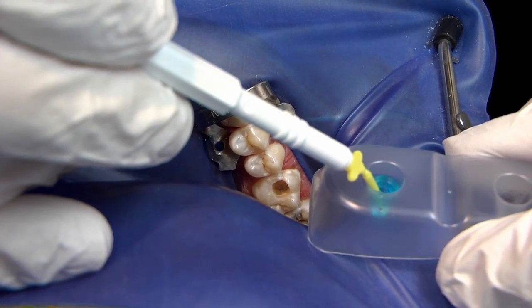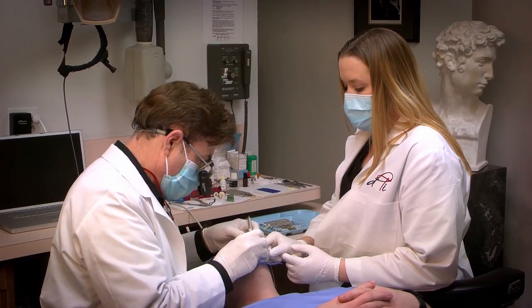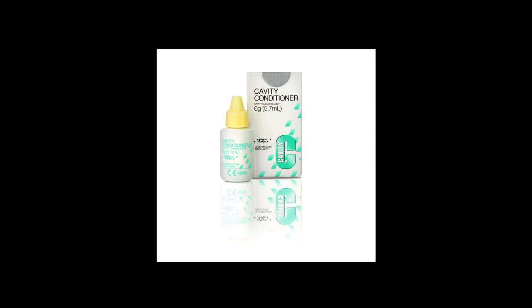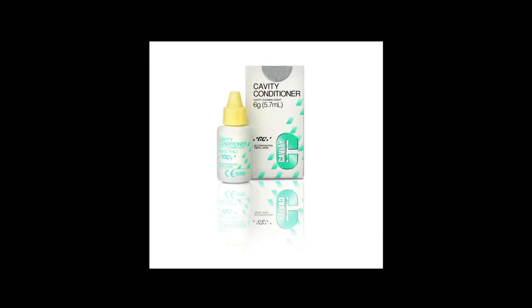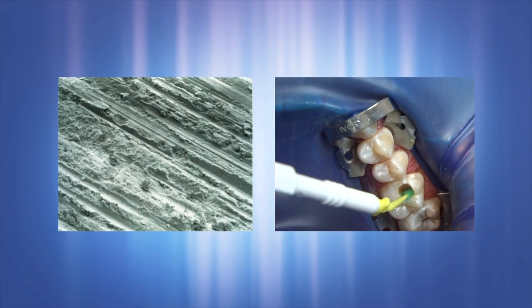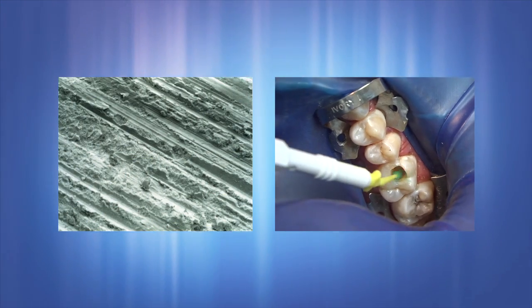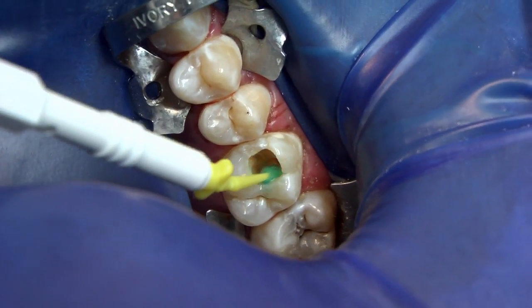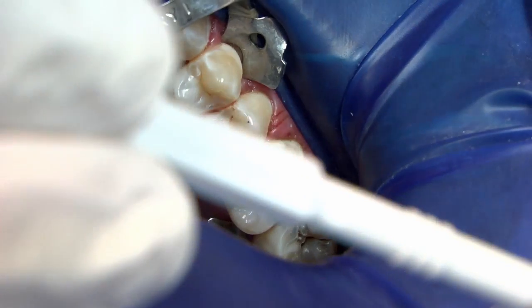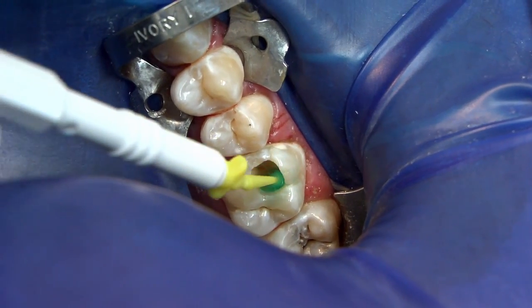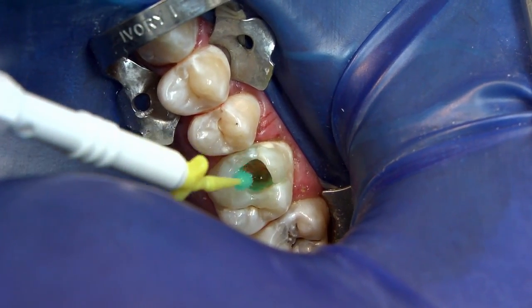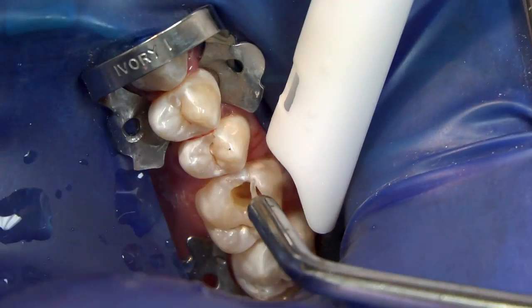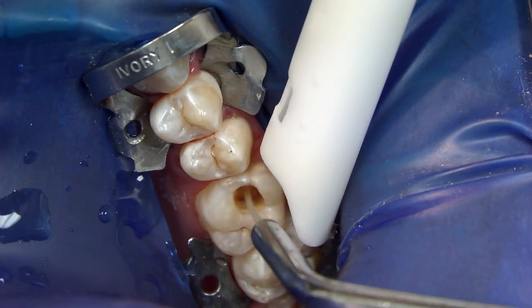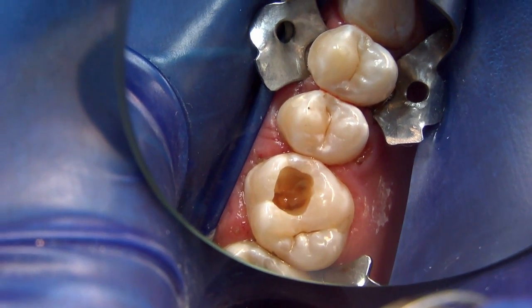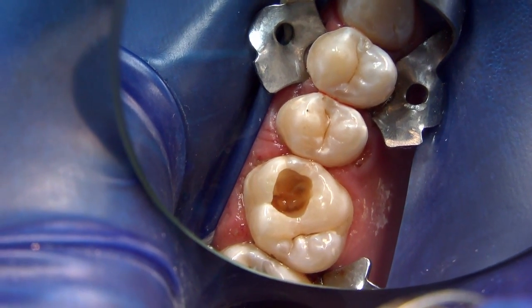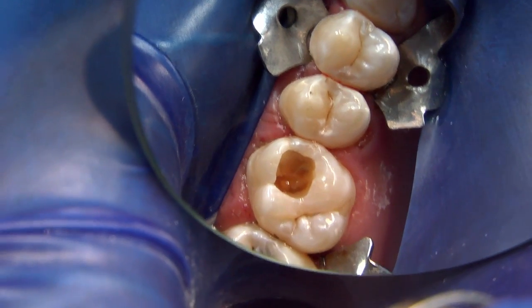This procedural step, tooth conditioning, is optional. If utilized, the GC cavity conditioner, a 10% polyacrylic acid, removes the smear layer and any contaminants while also providing additional micromechanical retention. The cavity conditioner is applied to the bonding surfaces using an applicator tip and allowed to dwell for 10 seconds, thoroughly rinsed with water and lightly air dried. It is important not to desiccate the dentin surface. It should appear moist with a glistening surface.